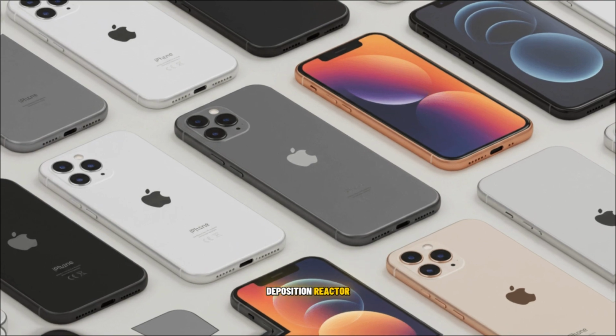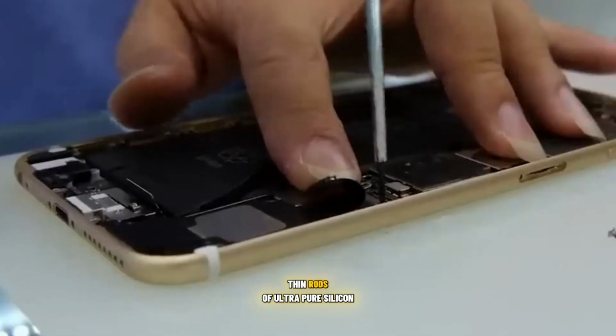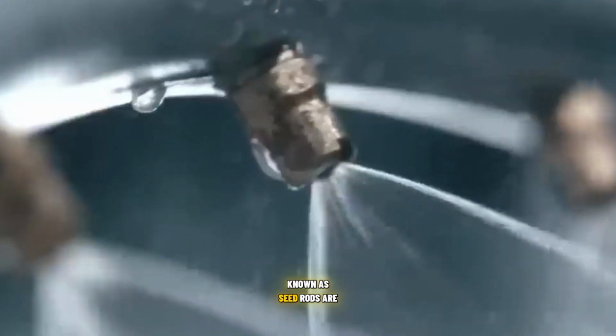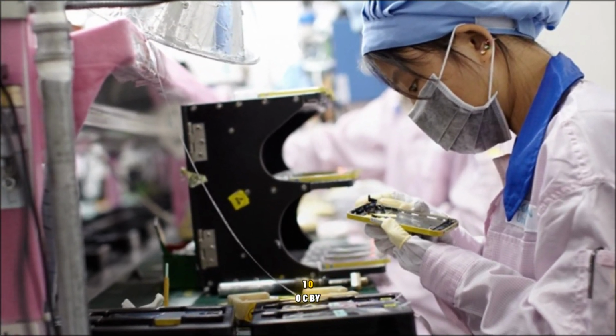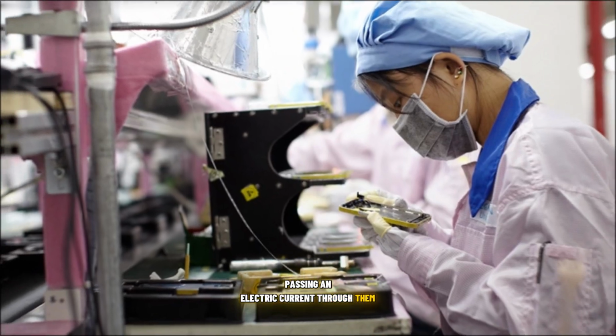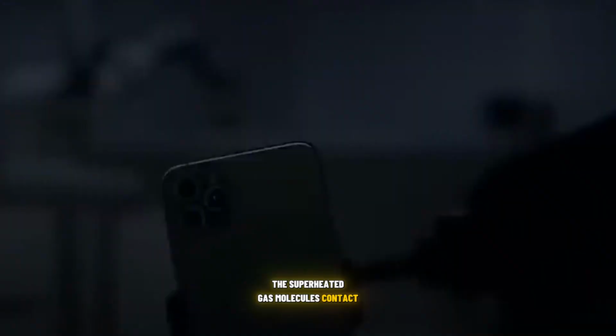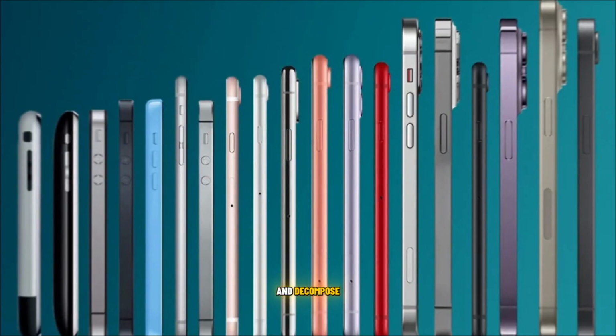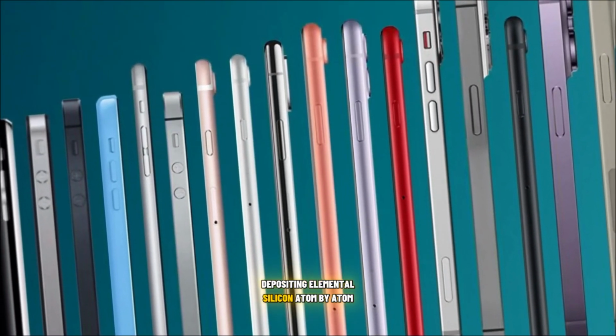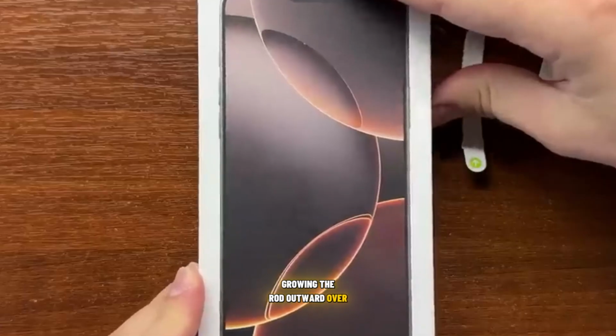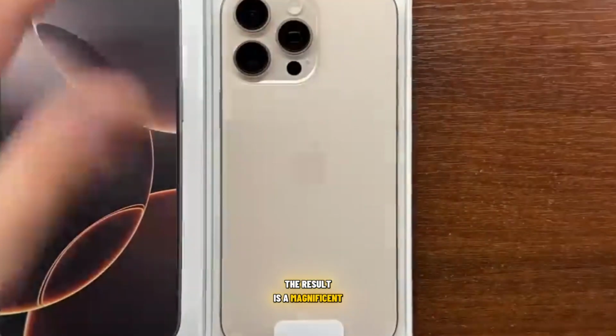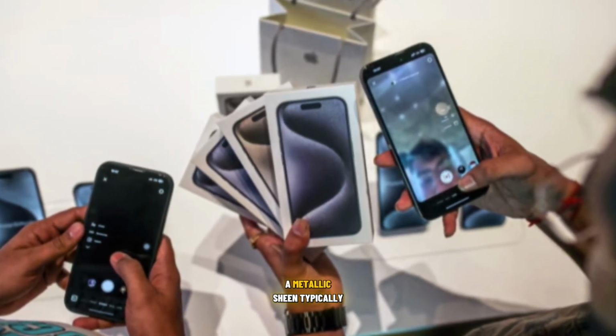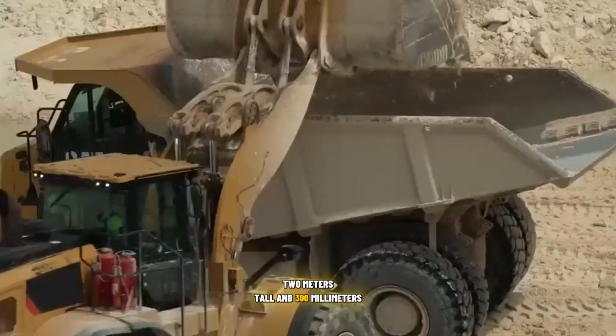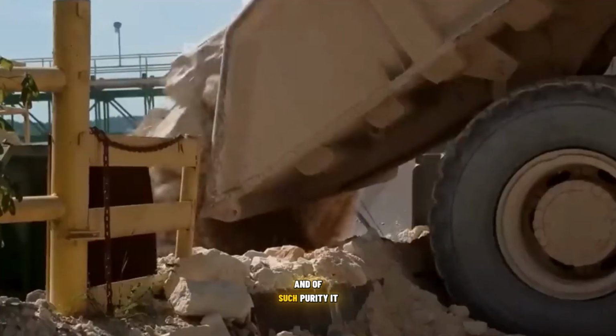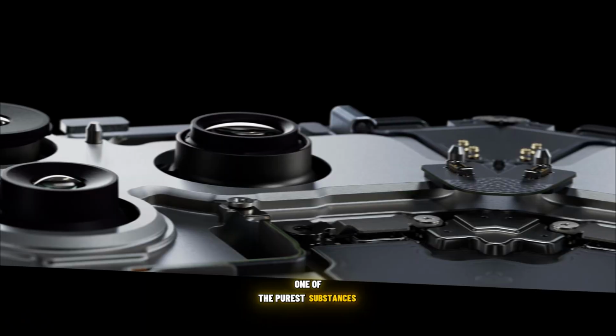this ultra-pure trichlorosilane gas is then introduced into the final deposition reactor. Inside this sealed chamber, thin rods of ultra-pure silicon, known as seed rods, are heated by passing an electric current through them. The superheated gas molecules contact the searing surface of the seed rods and decompose, depositing elemental silicon atom by atom, growing the rod outward over several days. The result is a magnificent, shimmering polycrystalline silicon ingot, or boule, with a metallic sheen, typically 2 meters tall and 300 millimeters in diameter, and of such purity it is considered one of the purest substances on Earth.